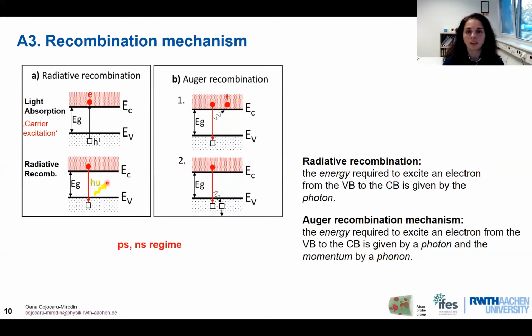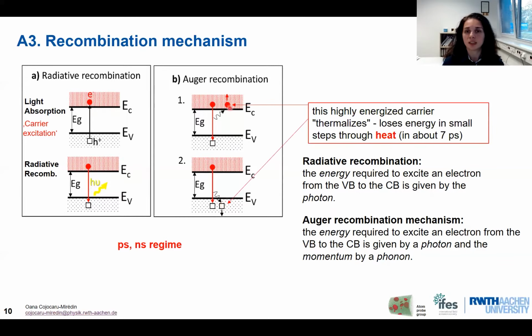Now we have the non-radiative recombination, which is no longer a two-particle process, but a three-particle process, because the energy released after recombining an electron from the conduction band and a hole from the valence band is released to a third particle. This can be either an electron in the conduction band or a hole in the valence band. And because these electrons are going to reach much higher energy levels, again we are going to have the same thermalization process. So we are going to have a loss of energy in very small steps and release this surplus of energy as heat inside our sample. So again, recombination inside our sample can also lead to supplementary heat inside our atom probe tip.